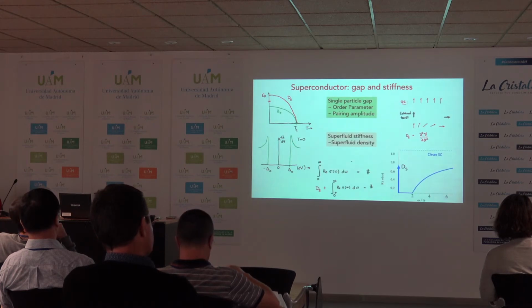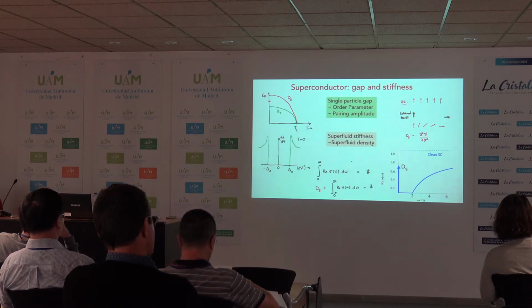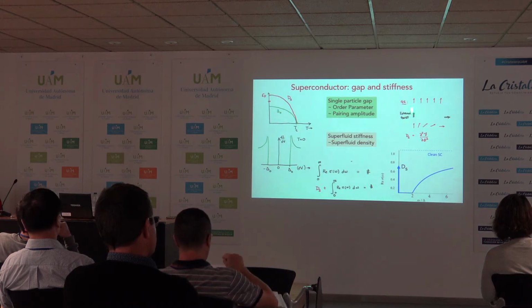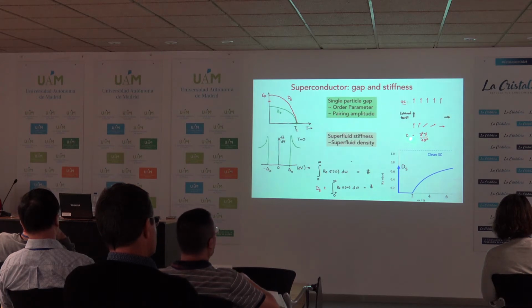Okay, so that's the first part. The second property, which is sensitive to the phase of the order parameter, is shown here. In the ground state at zero temperature, your phases are aligned. If you now twist the phases by applying some boundary condition, that forces these phases to adjust to this twist continuously, and that raises the energy. The increase in energy, the second derivative of the free energy with respect to this twist angle, is a very important defining property of the superconductor or the superfluid that I call the superfluid stiffness. And I kind of analogously call it the superfluid density.